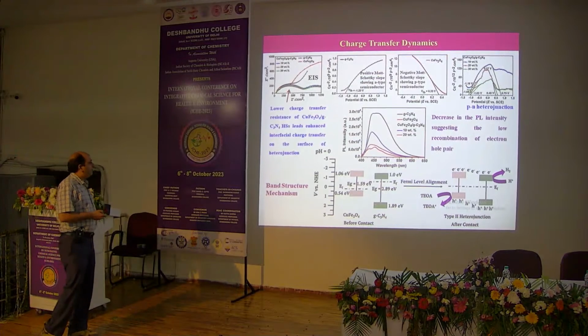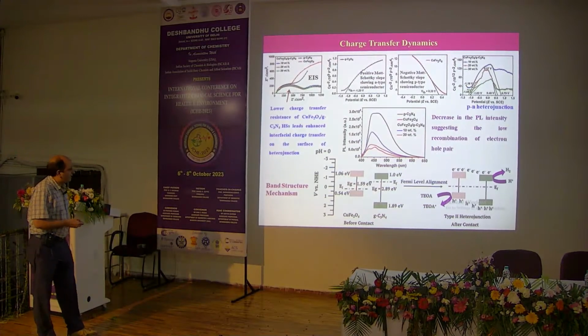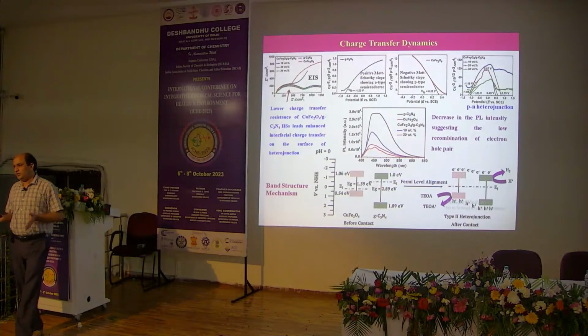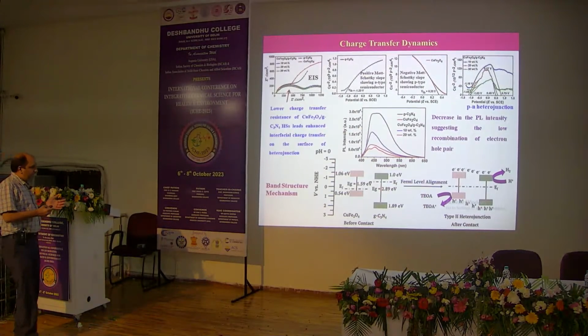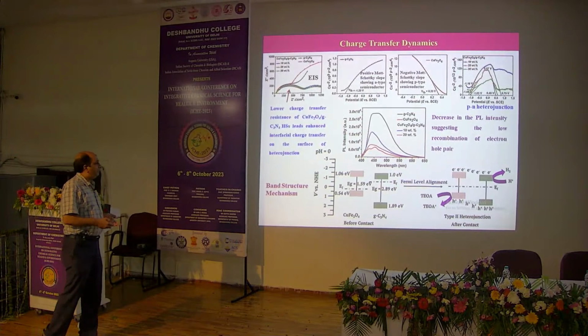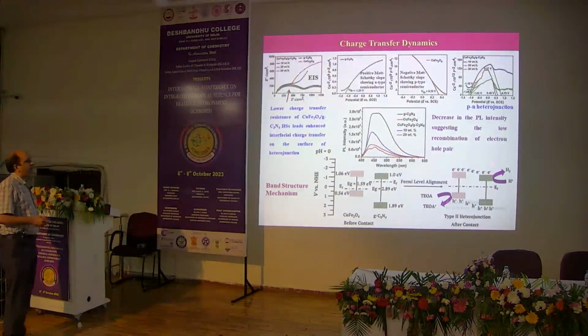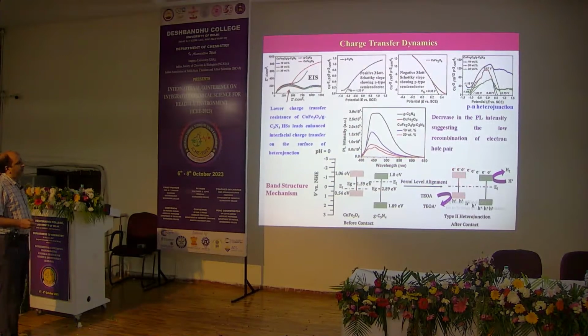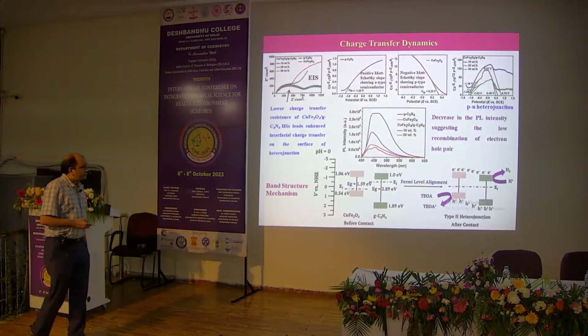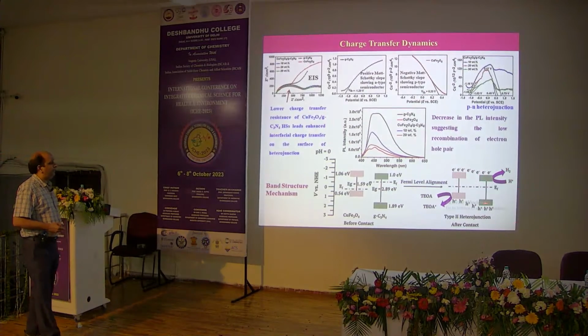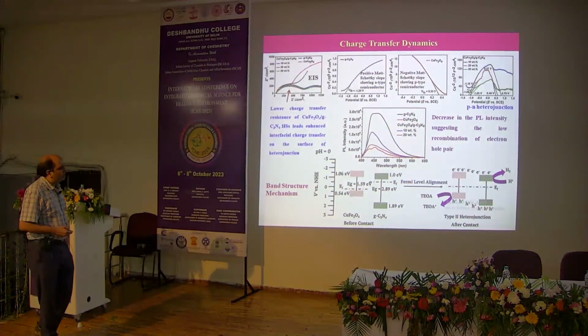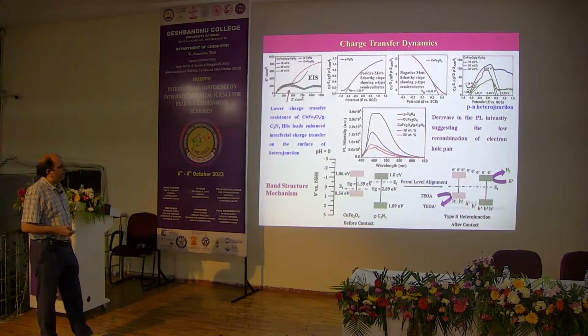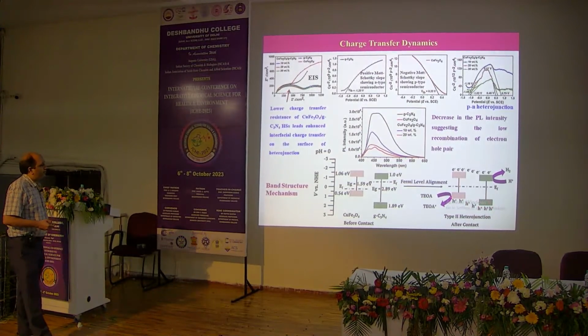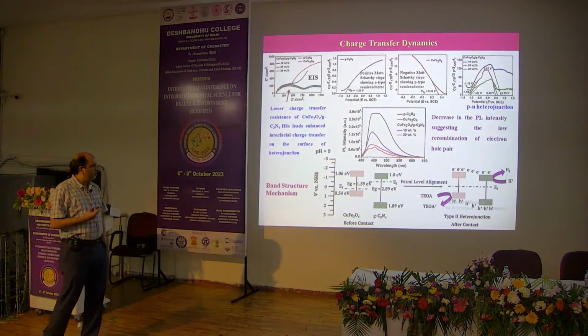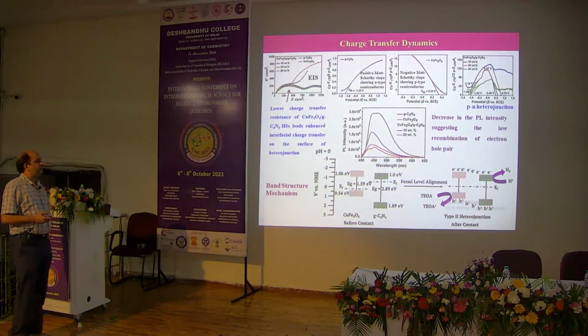Here it shows the band structure of the pure copper ferrite and the graphitic carbon nitride before the heterojunction formation, and when the heterojunction forms, the Fermi level band alignment occurs, and here the electrons from the conduction band of the copper ferrite tunnel to the conduction band of the graphitic carbon nitride, whereas the holes from the valence band of the graphitic carbon nitride transfer to the valence band of the copper ferrite, and these electrons are used to reduce the H plus into hydrogen gas.